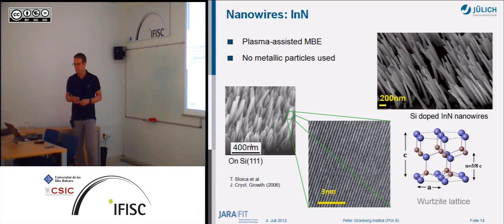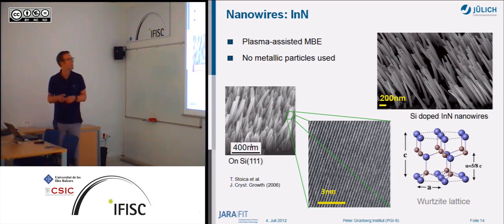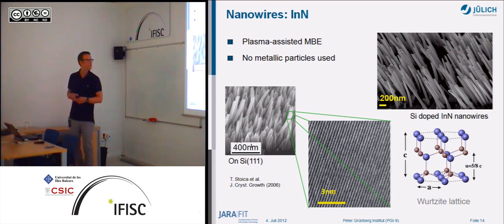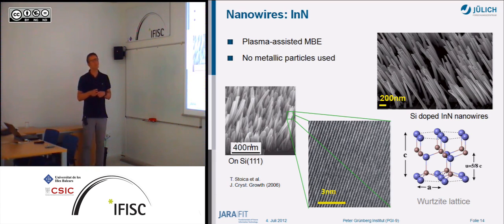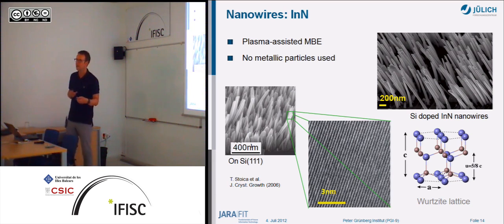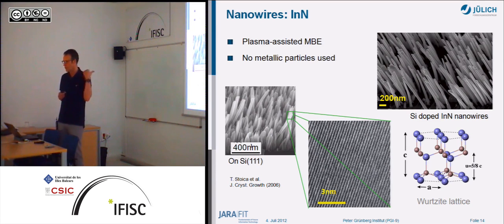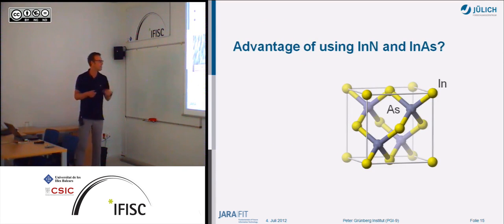Yeah, so that's something different compared to the method I showed before. The last one I want to show you is a different material. It's indium nitride. This is also grown by MBE, molecular beam epitaxy. So these are a typical example of indium nitride nanowires, and indium nitride usually has wurtzite structures. So this is compared to indium arsenide, a different material. You have different band structure, and you will see later why this is maybe interesting for nanowires.